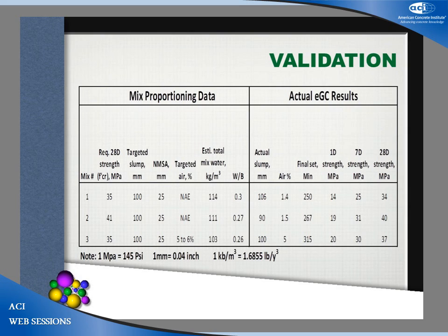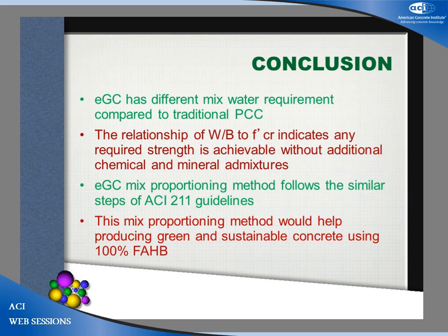Second is the non-air-entrained concrete, 41 MPa, and that also matched very well. And the last one is the air-entrained concrete, 35 MPa target, and that also gave a good result. So this mix design is validated very well.